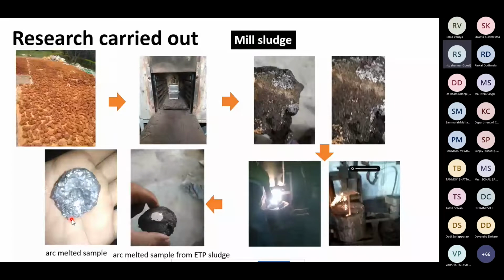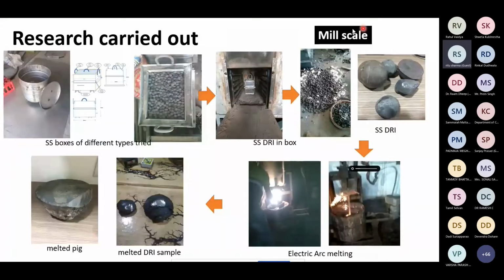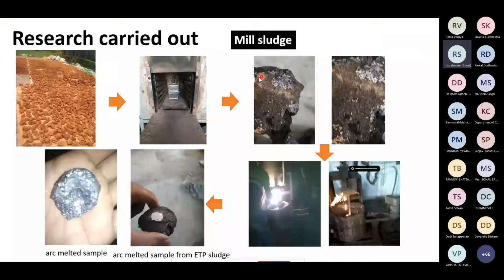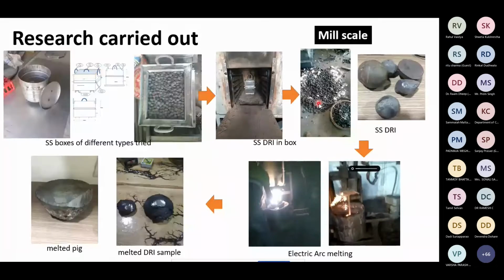Now, this study we carried out for the mill scale. For the mill sludge, the study was carried out in the same pattern. Mill sludge is taken out from the filter press. We made small lumps of it, put it in the stainless steel box inside the furnace, and heated it to 1600 degrees centigrade. Here also we have added the flux. Sludge plus flux is there, and here we have the mill scale plus fluxes.